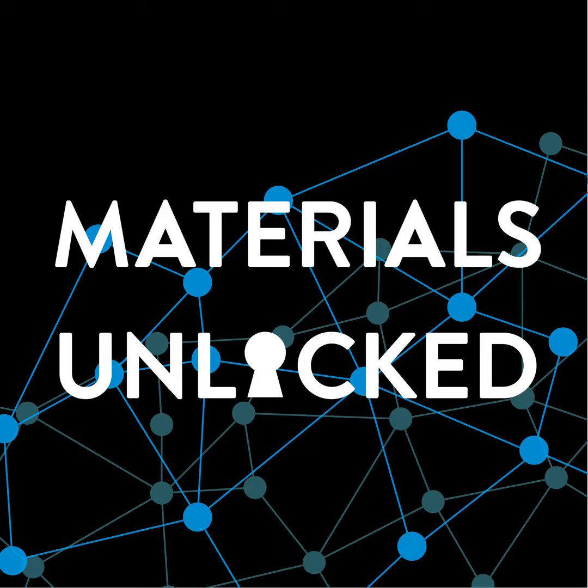Some particular types of steel undergo a phase transformation. So this is a rearrangement of the atoms inside the material. And they go through this either because of how they've cooled down or because of deformation. One of the interesting things with this particular behaviour in steel is that it's a transformation of something which is weak and ductile, so something that yields quite early but is quite flexible and can be deformed for a long period of time and a large amount of deformation. It transforms from that kind of behaviour to something which is strong and brittle. So strong but likely to shatter very easily. Yeah, as opposed to something that's soft and bendy.